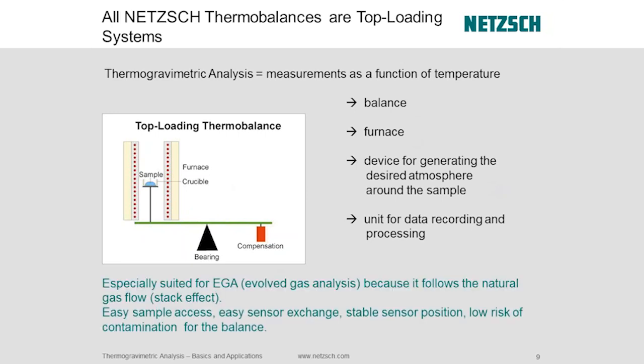Okay. This top-loading design is really nice. It's especially well-suited for things like evolved gas analysis because gases by nature want to flow upward. Okay, they want to go up. And so the way the NETZSCH instrumentation is designed, the balance sits down below. The purge gas comes in here at the neck, and the gases evolve from the sample, follow the purge gas up and out. So it's really great because we don't have issues with contamination.